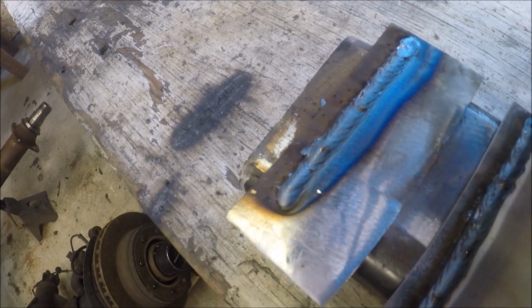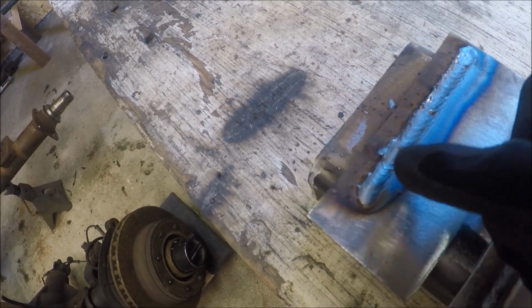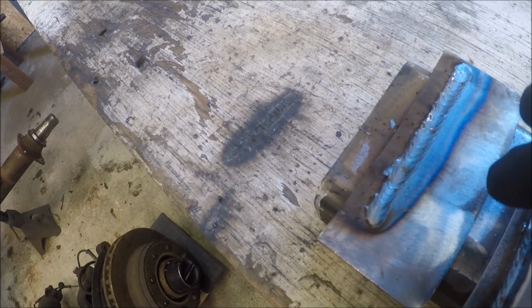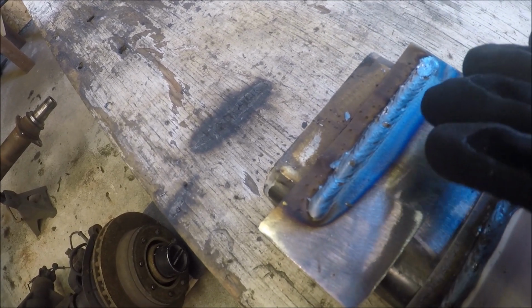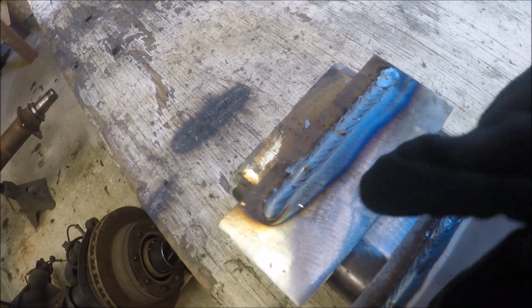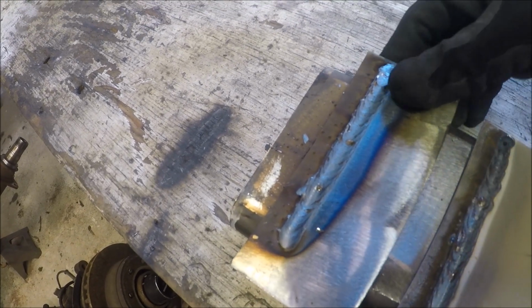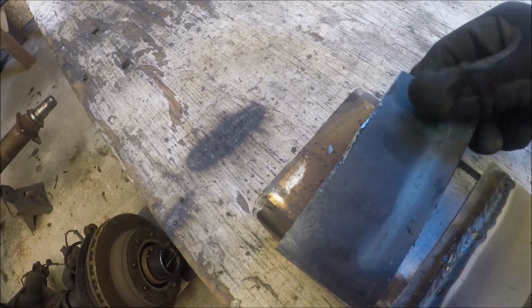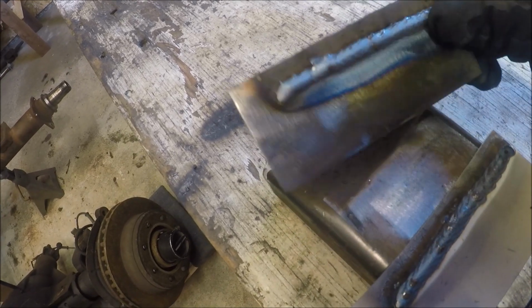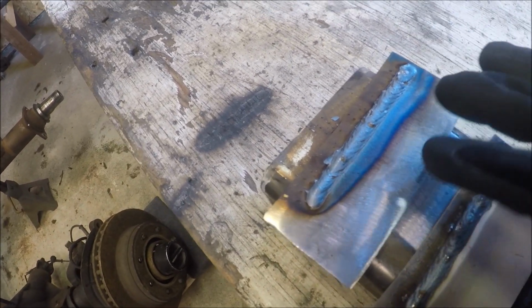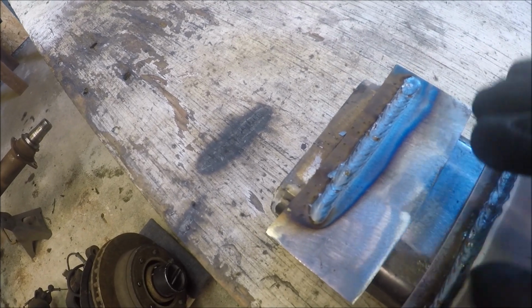And this looks like a pretty good weld. I'm pretty happy with it. One little spot right here where that was probably my fault. I got a little bit too close to the metal, but this is a good, clean, uniform weld. You can see the transfer of heat very good with the rainbowing across. If I flip it over, you can clearly see that I got good penetration. There's no real visible porosity. And this is a good weld to me.